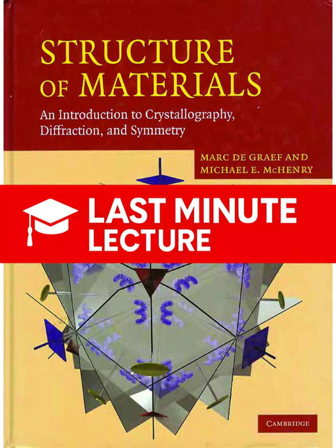But then if we look at the 200 reflection for that same structure, the peak reappears. Why does just doubling the indices change the interference pattern so drastically? It's all about the path difference again. The plane spacing for the 200 planes, d200, is half that of the 100 planes. Right. So if the plane spacing is halved, the corresponding path difference for the wave scattered by that atom at 1/2, 0, 0 is doubled.